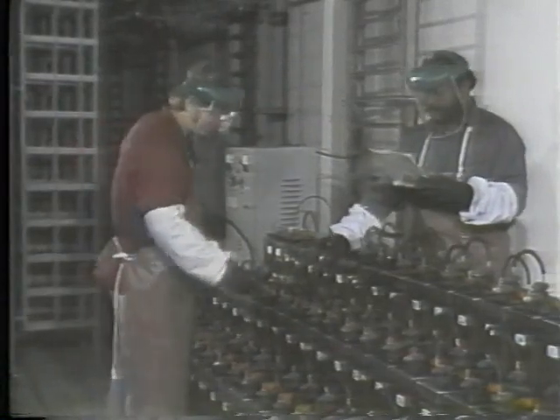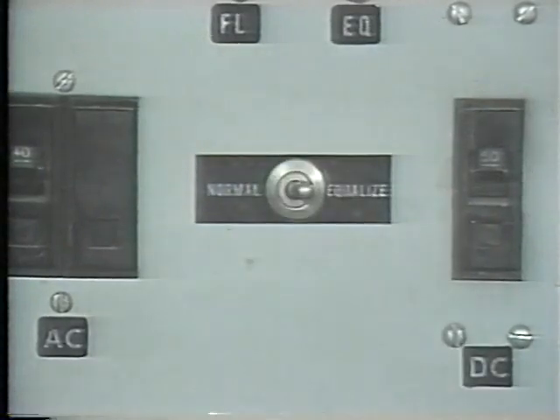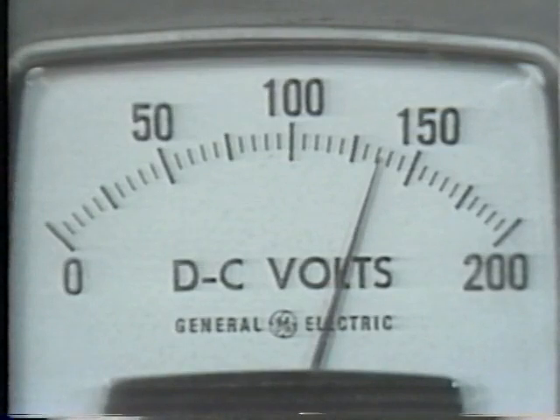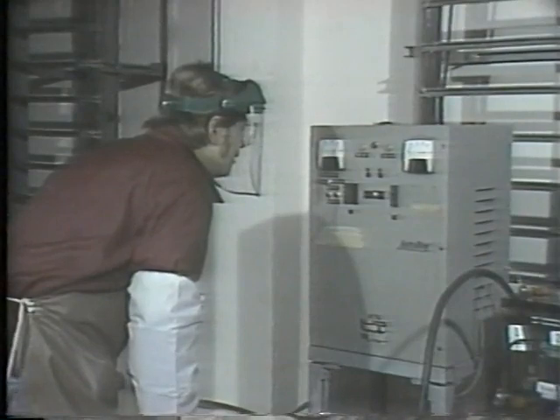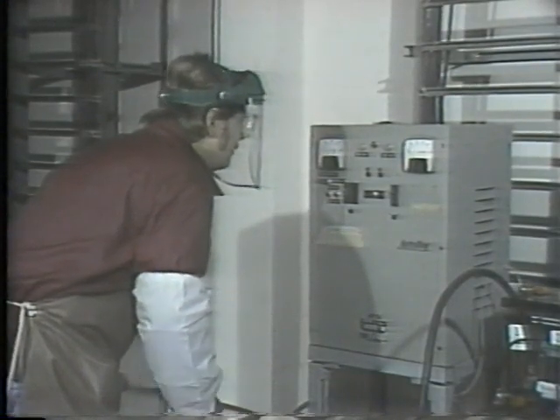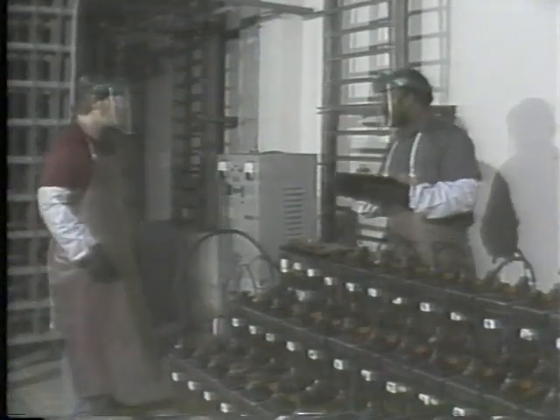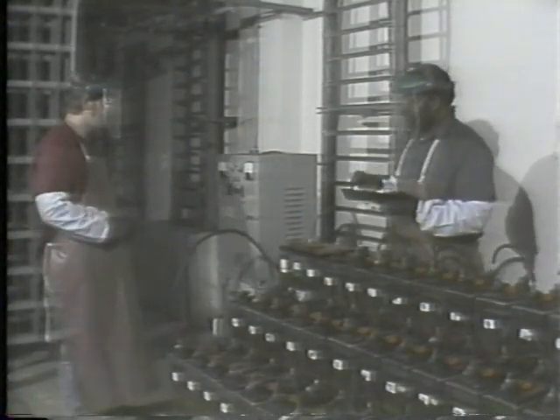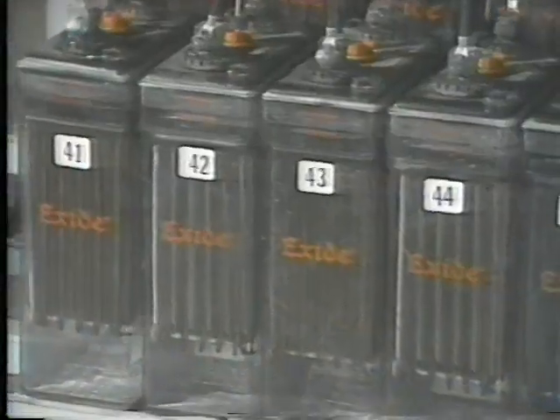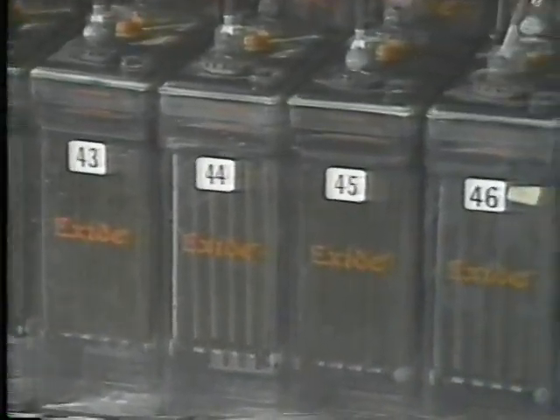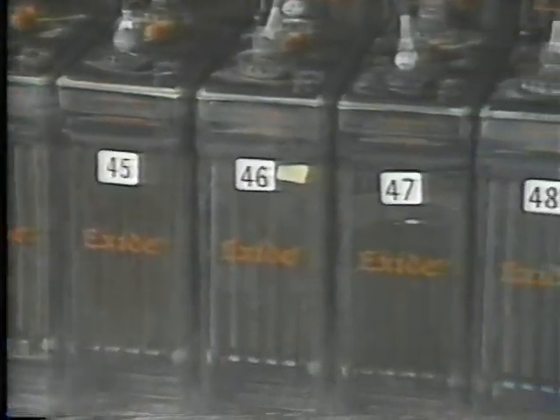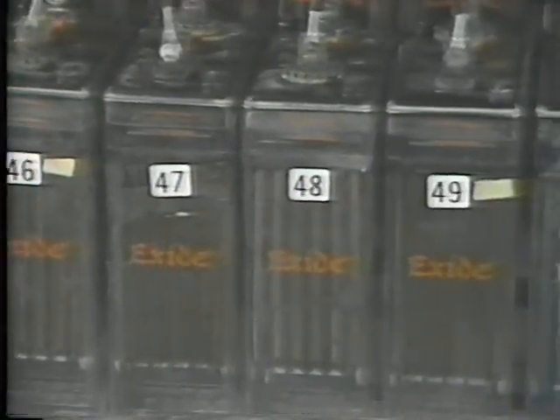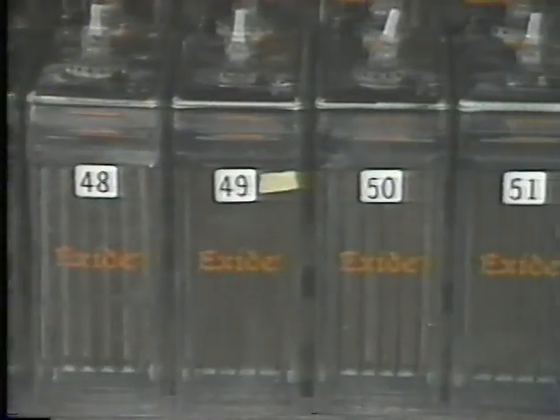The first logical step is to put the battery on an equalizing charge. On this charger, moving the selector switch from float to equalize raises the bus voltage from 130 volts to 138. That means that individual cell voltage is increased from 2.25 volts up to 2.38 volts per cell. This increased cell voltage is intended to drive the last bit of sulfates off of the plates. It's an extended charge to return the battery to like-new condition.